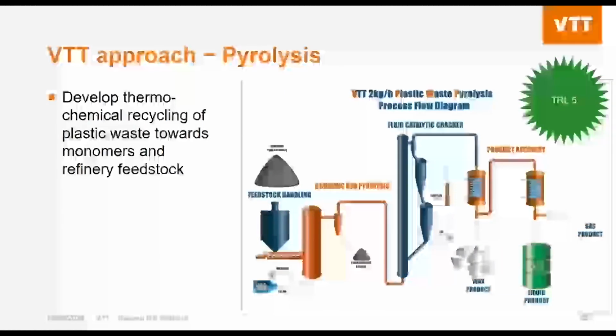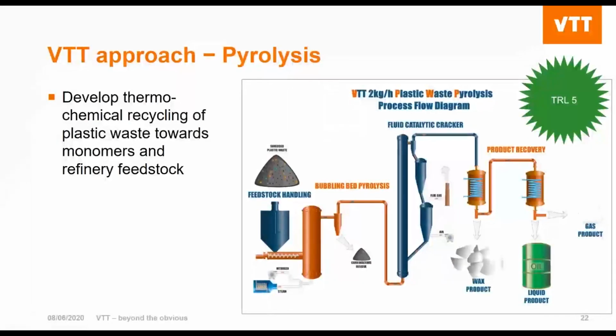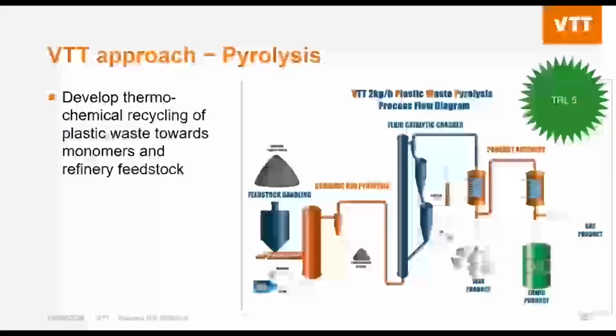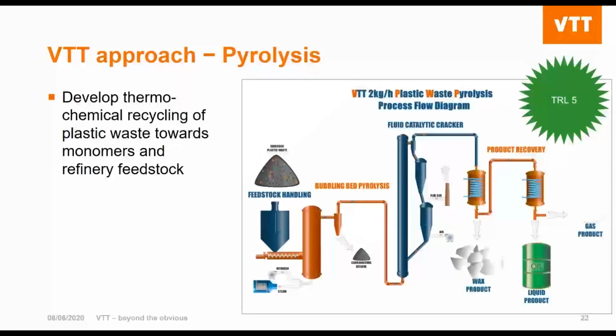And we at VTT actually have a state-of-the-art infrastructure from lab to bench to pilot scale. So, to take a look at this flow diagram, just to give you the basics, pyrolysis is a process where the material is chemically decomposed at elevated temperatures in the absence of oxygen. So the feedstock is fed into the pyrolysis bubbling bed unit, and then it's further processed at the fluid catalytic cracker where we can optimize the yield for wanted products. And the products that we do get out of pyrolysis are, of course, char, waxes, but the most important ones are the oil and the gas. But of course, we also are looking at these rather side stream like the waxes, what kind of optimum uses we can have for them. And the TRL level of this catalytic pyrolysis reactor is currently around 5.